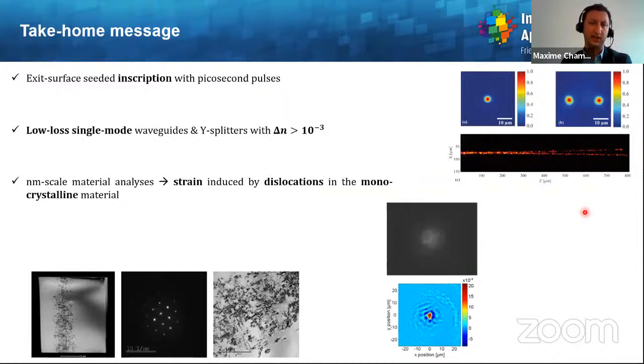And here is the take-home message. First, we have demonstrated the exit surface seeded inscription of waveguides with picosecond pulses. The waveguides are low losses and the refractive index change is higher than 10 to the minus 3. And the nanometer scale analysis allowed us to claim that some strain was induced by the dislocations provoked by the laser pulses in the monocrystalline material.